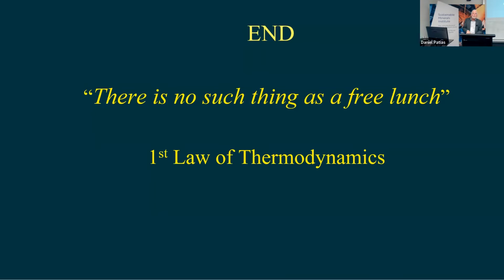So the extent to which we can do any better than that remains to be seen, other than where one concentrates the energy. And to some extent, I suspect that's what's happening with microwave pulsing and electroshock therapy, I call it, for the other technique, is being able to concentrate that energy at the flaws inside the rock. So you don't actually have to deform the entire rock to get to the point where you end up with tensile breakage. You concentrate that energy in a localized position, and that's where you save the energy. How on earth you do that is another matter.